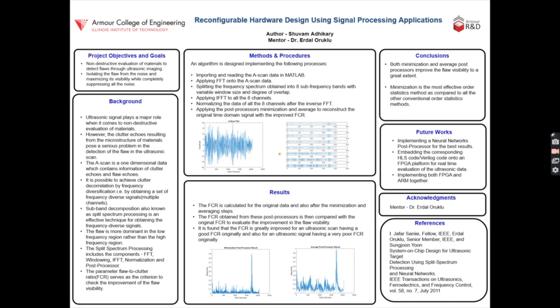It is found that the FCR is greatly improved for an ultrasonic scan having a good FCR originally and also for an ultrasonic signal having a very poor FCR originally. It can be concluded that both minimization and average post-processors improve the flaw visibility to a great extent, and also that the minimization post-processor is the most effective order statistics method as compared to all other conventional order statistics methods.